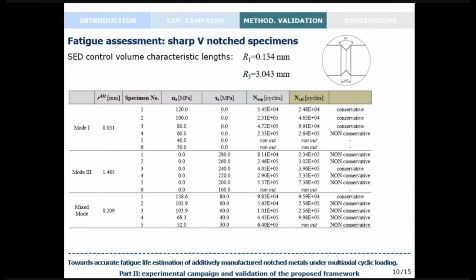So now that we have all the data necessary for the application of the analytical methodology, we can see the results. And in this slide, the results related to the sharp V-notched specimens are shown. At the top, you can see the said control volume characteristic length. And then by means of the equation shown at the beginning of this presentation, we computed the critical distance with this value here, obtaining a very small value of 0.03 millimeters for mode 1 loading and about 1.5 and 0.2 millimeters for mode 3 and mixed mode loading.